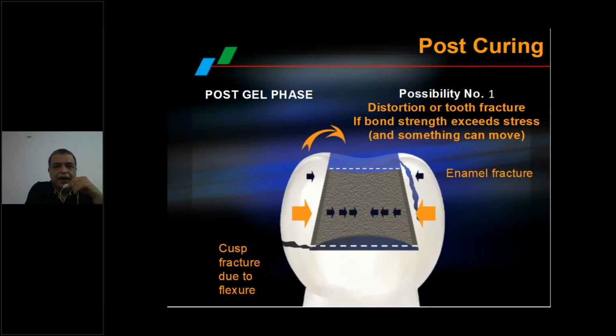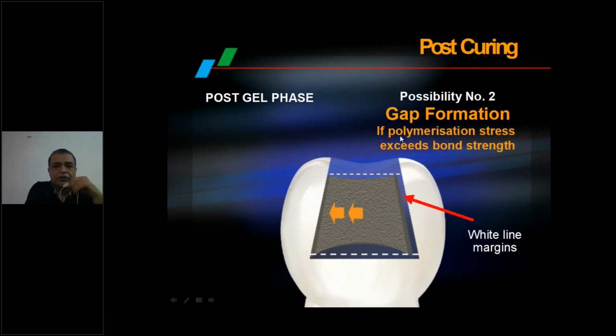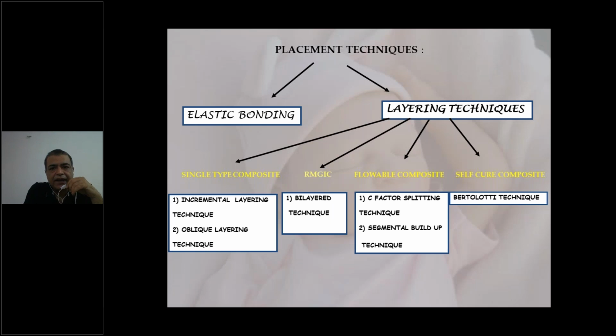So this is what I was trying to explain, that when you put composite, especially in bulk, inside a cavity like this, and you try and cure it, the composite shrinks. So what happens? It can lead to cuspal fractures, it can lead to enamel fractures, or in a far-fetched scenario, if the polymerization stress exceeds the bond strength, you can have these white line margins because composites will leave some amount of the wall. So how do you manage that? There are multiple ways to manage this polymerization shrinkage, and in my personal opinion, the only clinical technique is using an incremental layer and oblique layering technique.